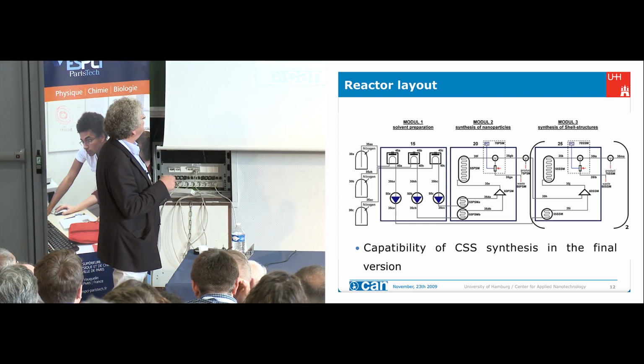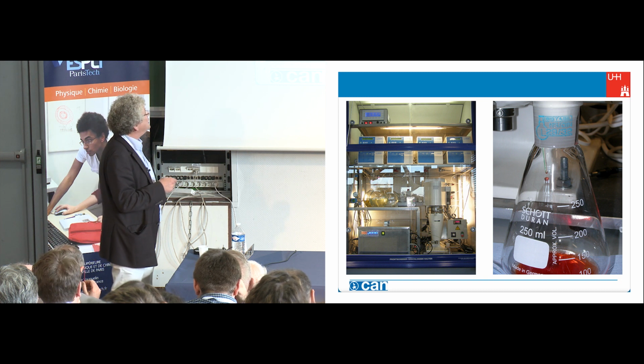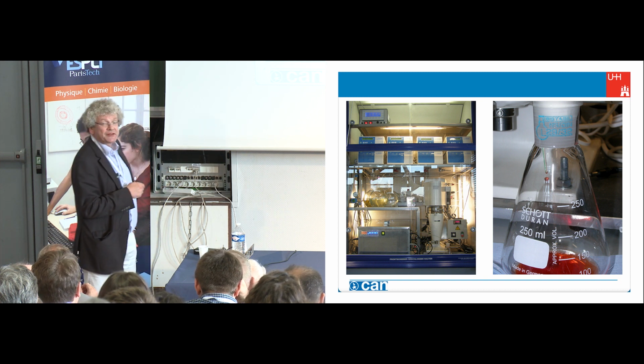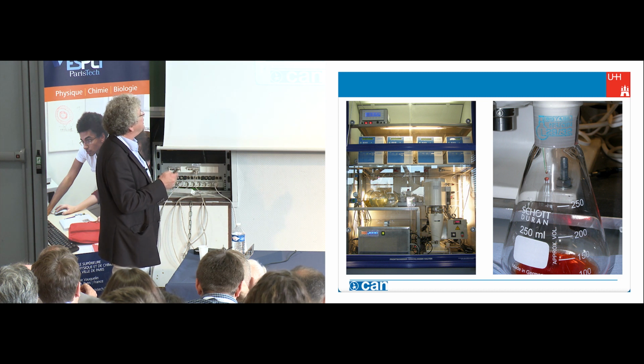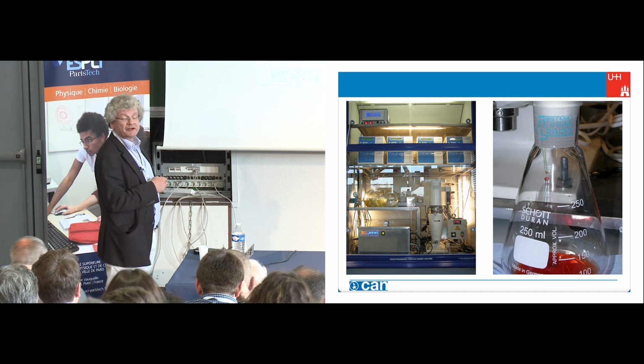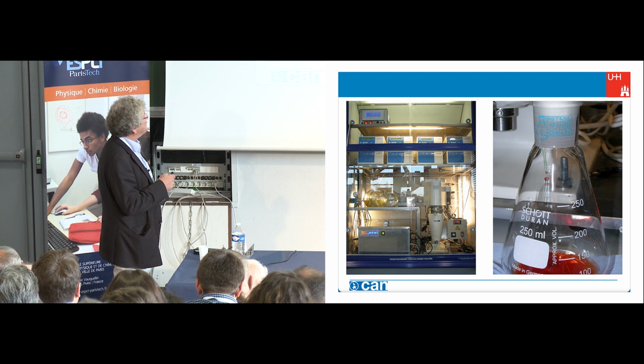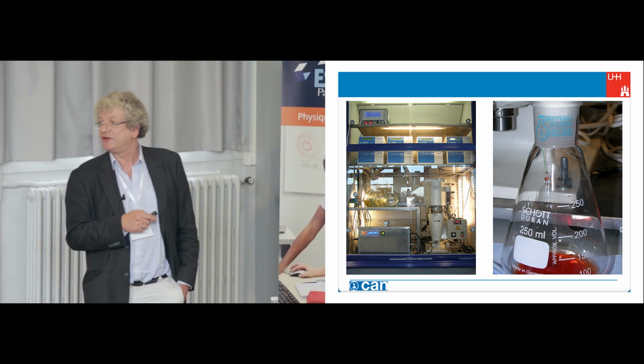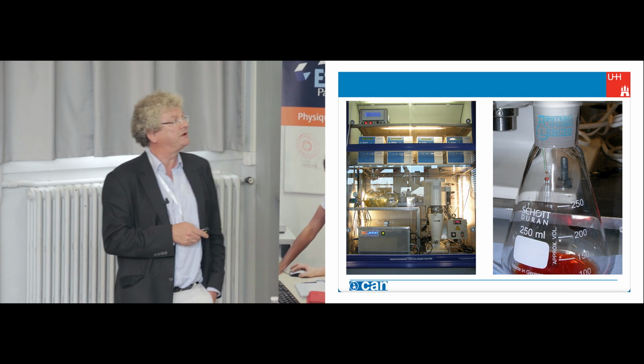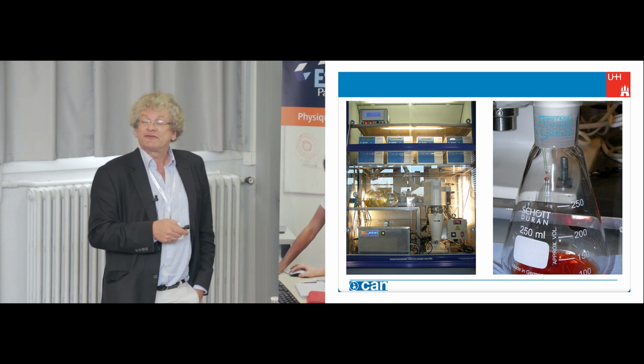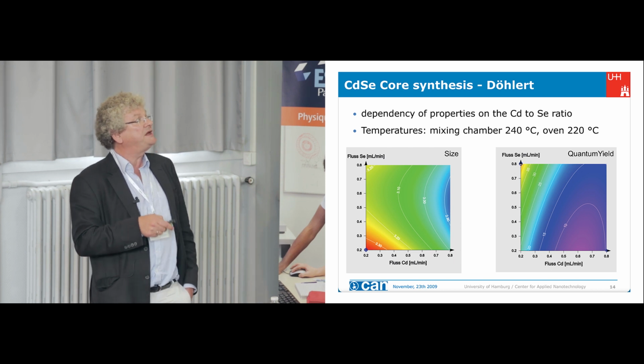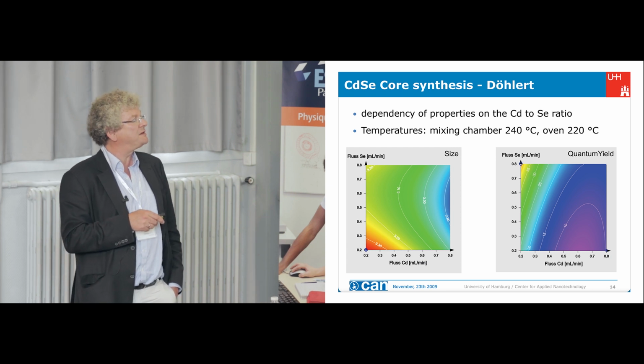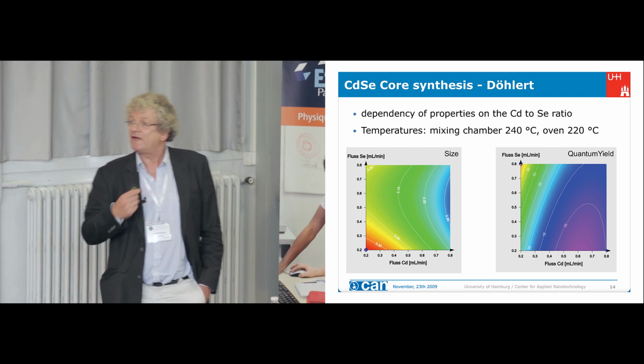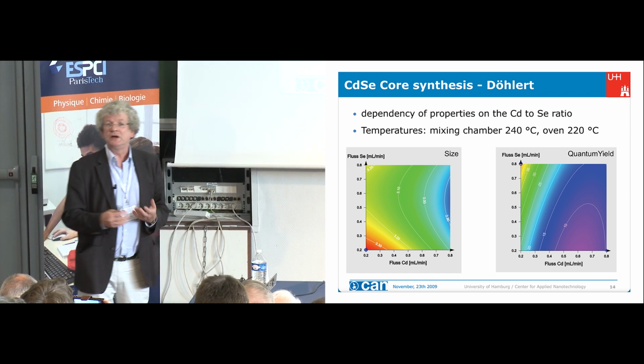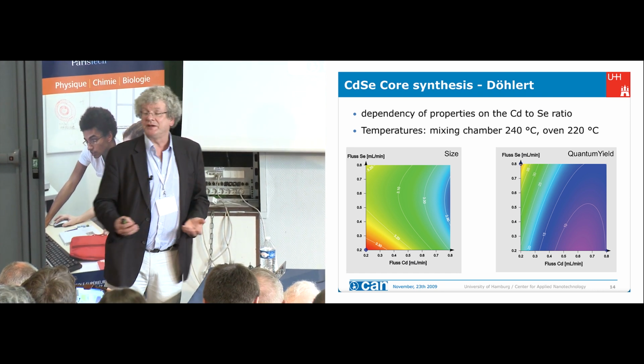So here's one of these analytic things in the lab scale. So we can produce with these things something like today, it's in the order of 100 grams or so per day, but we can easily scale it up to about 1 kilogram per day, pure quantum dots, depending a little bit on the material. And the good thing is, of course, you have then parameters of flow speed and mixing ratios. You see how the quantum efficiency of the particles comes out, how the size of the particles comes out. Everything is in the computer, and therefore there is no human parameter anymore in it.